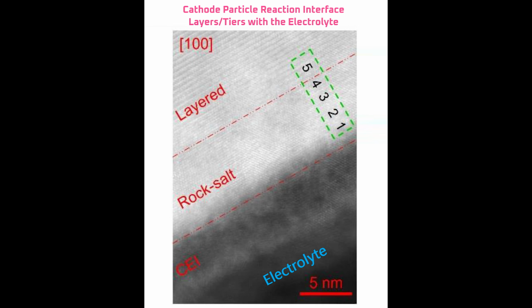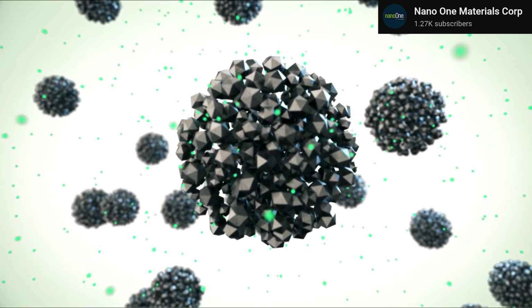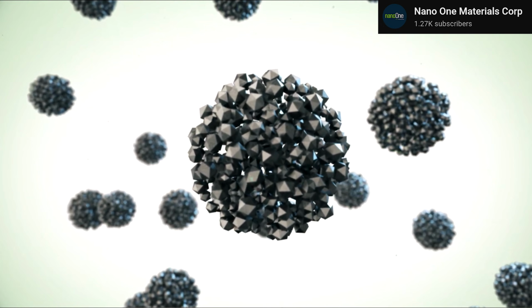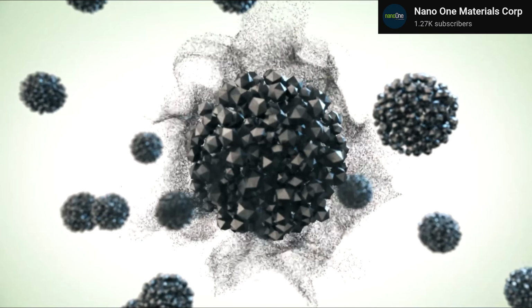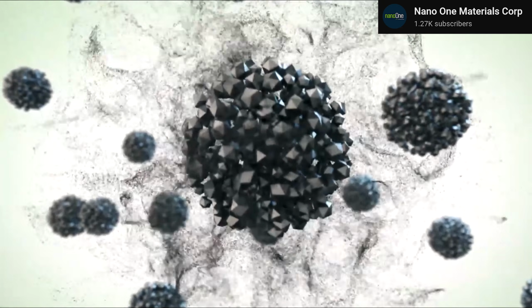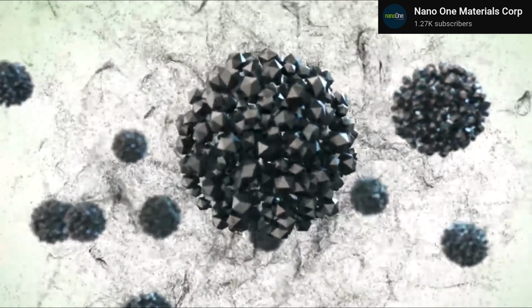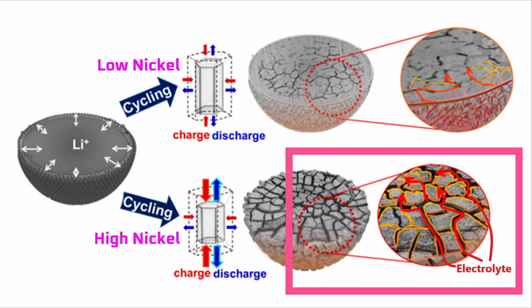Getting back on track, between 4.2 volts and about 4.5 volts, the nickel-based cathode particles and conductive carbon particles start reacting with the electrolyte to produce a variety of solids, liquids, and gases that reduce the cycle life of the battery. Then, above 4.5 volts, the degradation becomes more aggressive. The nickel-based framework of the cathode starts dissolving into the electrolyte, which poisons the electrolyte solution, and the cathode crystal starts cracking and collapsing, which further accelerates the dissolution.